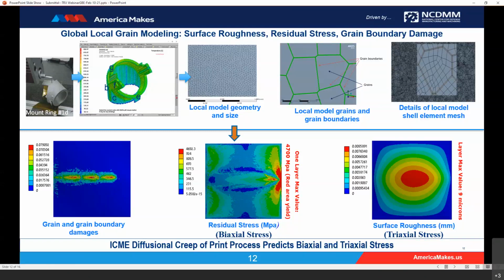As you can see on the left, we have an actual mount ring, and this image right next to it is the virtual full mount ring, which is subjected to temperature changes and the overall behavior. That global information is transferred to our local model, and then running a localized, actual finite element analysis with the detailed shell elements for that grain, we can then predict the impact of global behavior on local behavior, and then translate that into grain boundary damage, residual stress, and surface roughness.